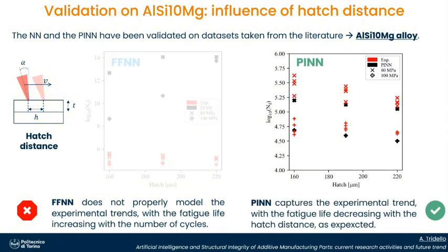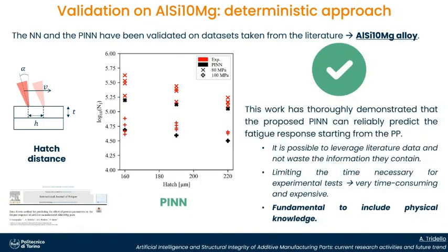With the physics-informed neural network, we can capture this trend, and the data are very close to the experimental one, which are those in red. Okay, so we are able to predict a trend which is widely known in the literature. So to conclude this first activity, this work has demonstrated the proposed physics-informed neural network can reliably predict the fatigue response starting from the process parameter. It is possible to leverage literature data, otherwise they are waste.